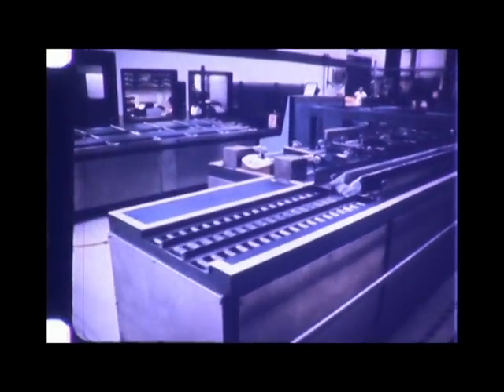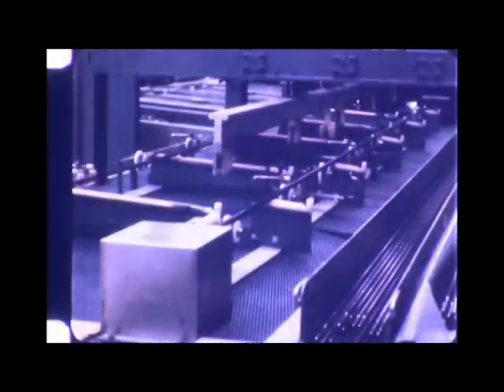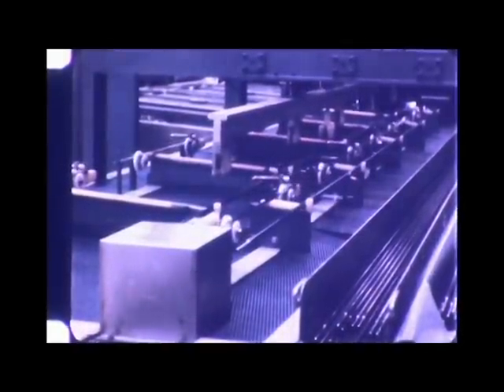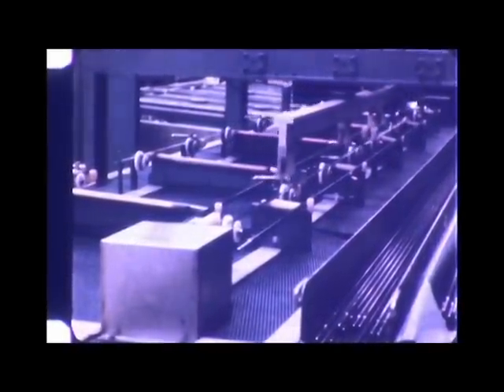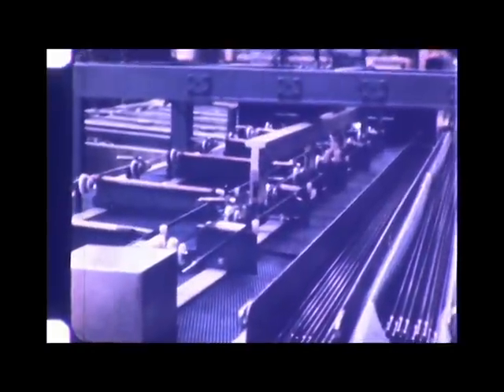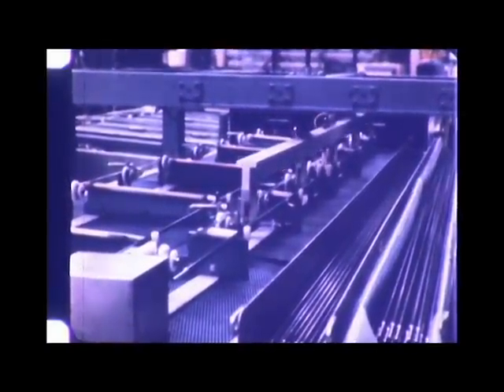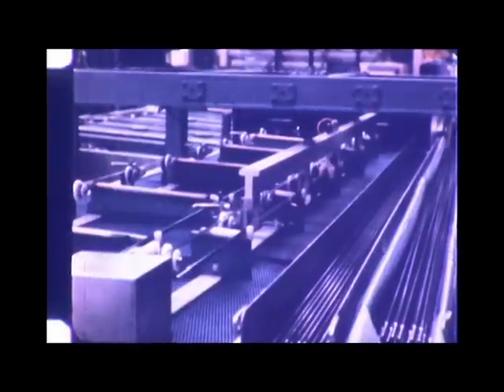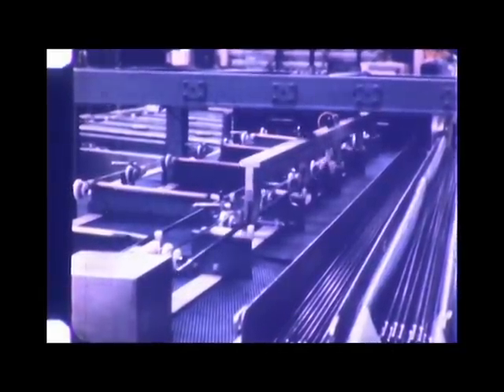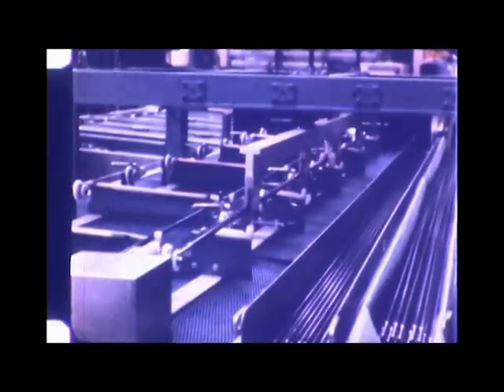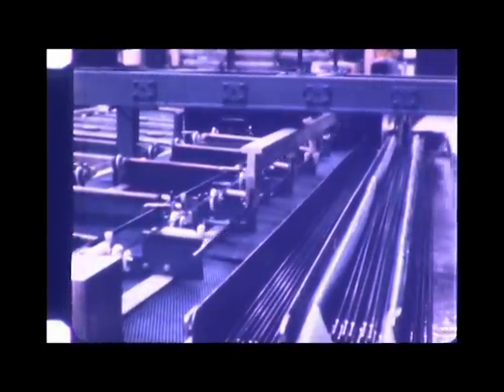The superconducting magnetometer also senses the space between pellets, presence of the getter, and presence of the hold-down spring. MAPS is fully automated, from material handling to data accumulation, data reduction, and data reporting. After magnetic scanning, and still under computer control, the fuel rods are transported to the passive scanning station, where the enrichment level of every pellet is measured, and the total uranium and U-235 content of each fuel rod determined.